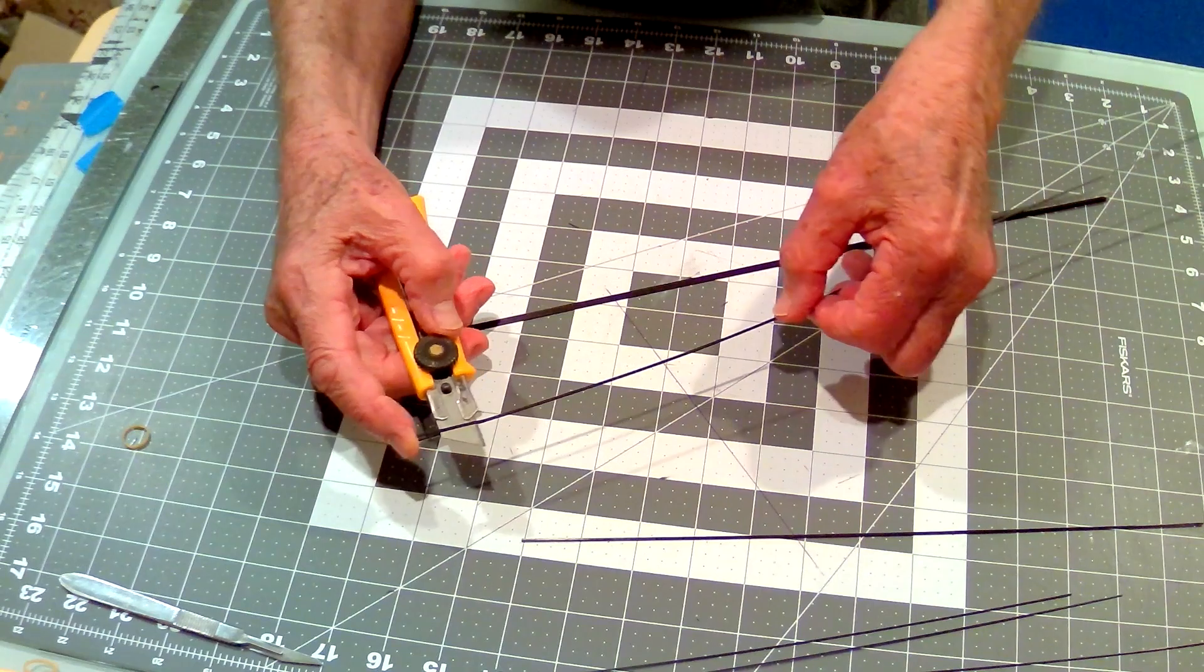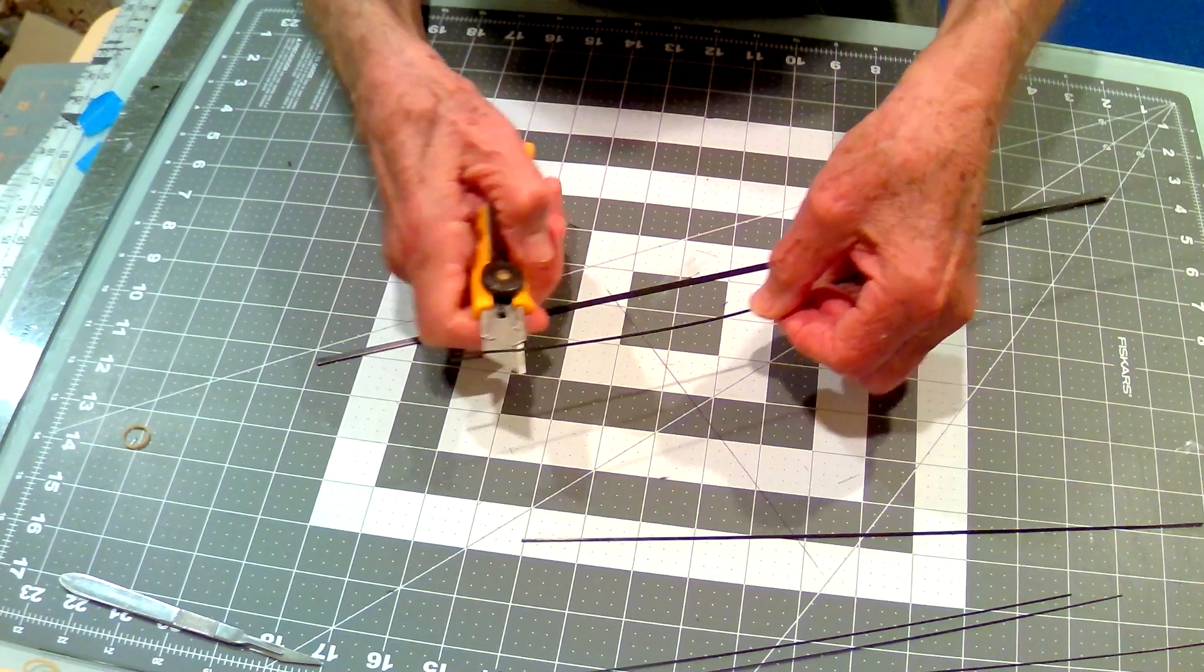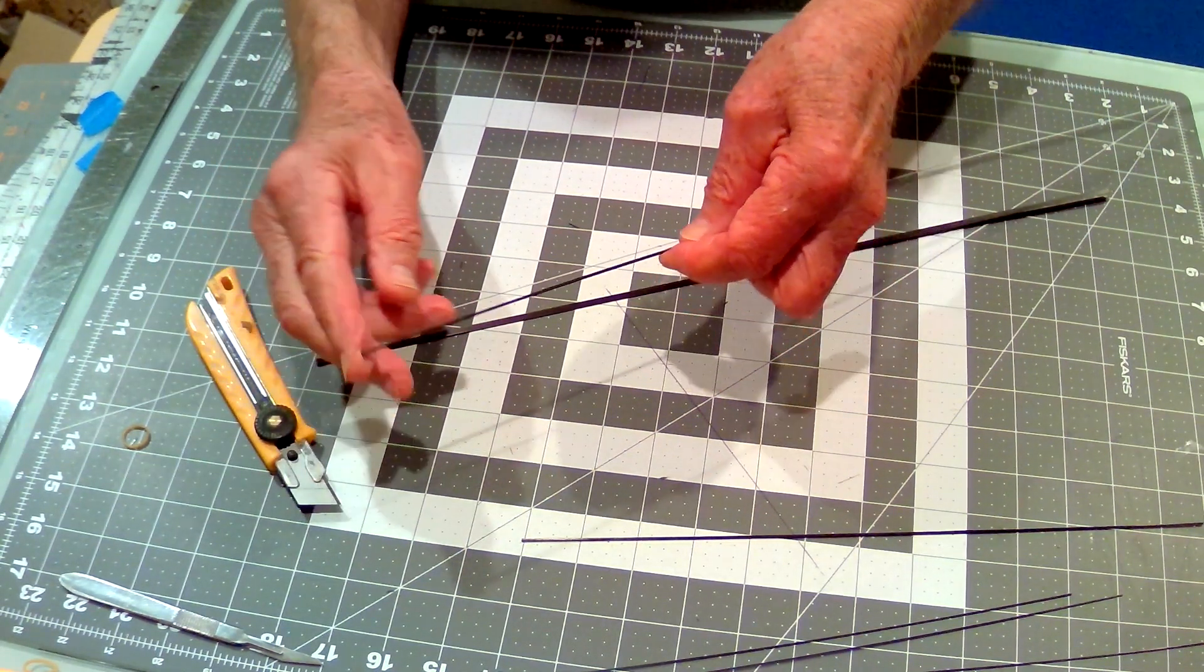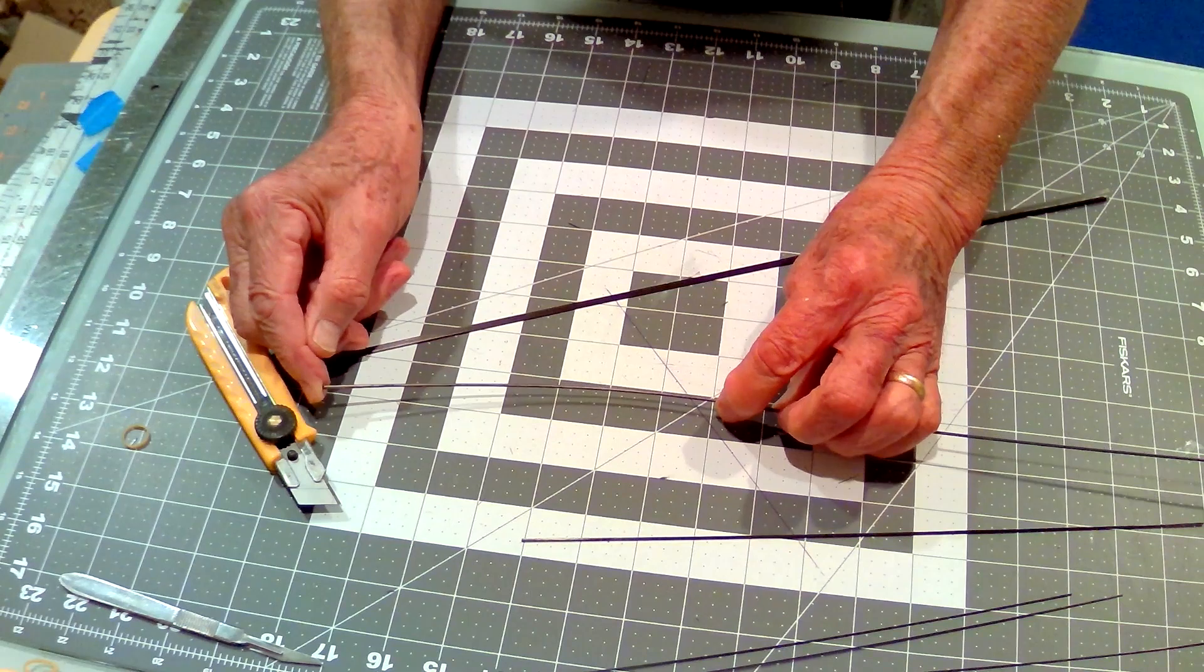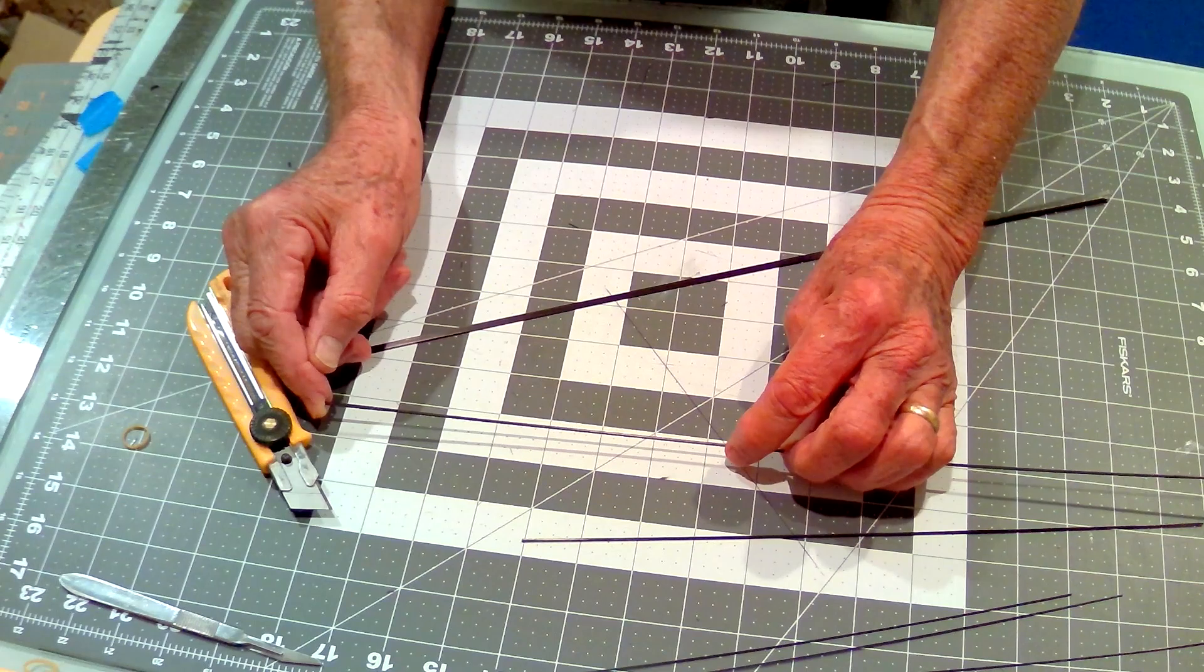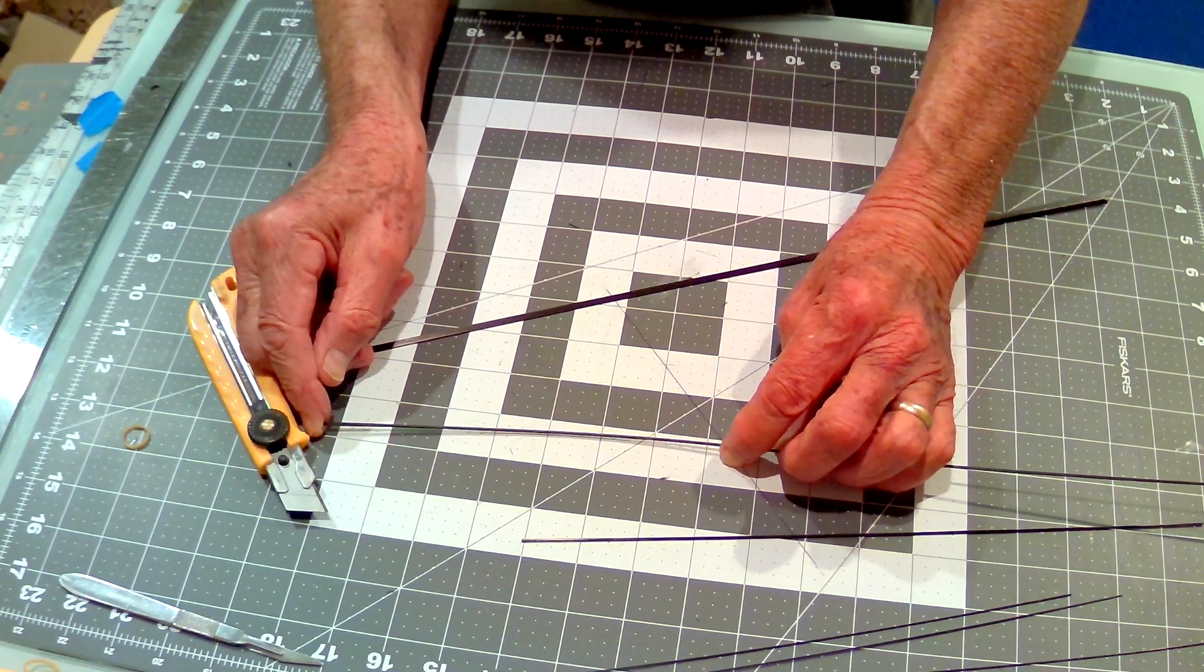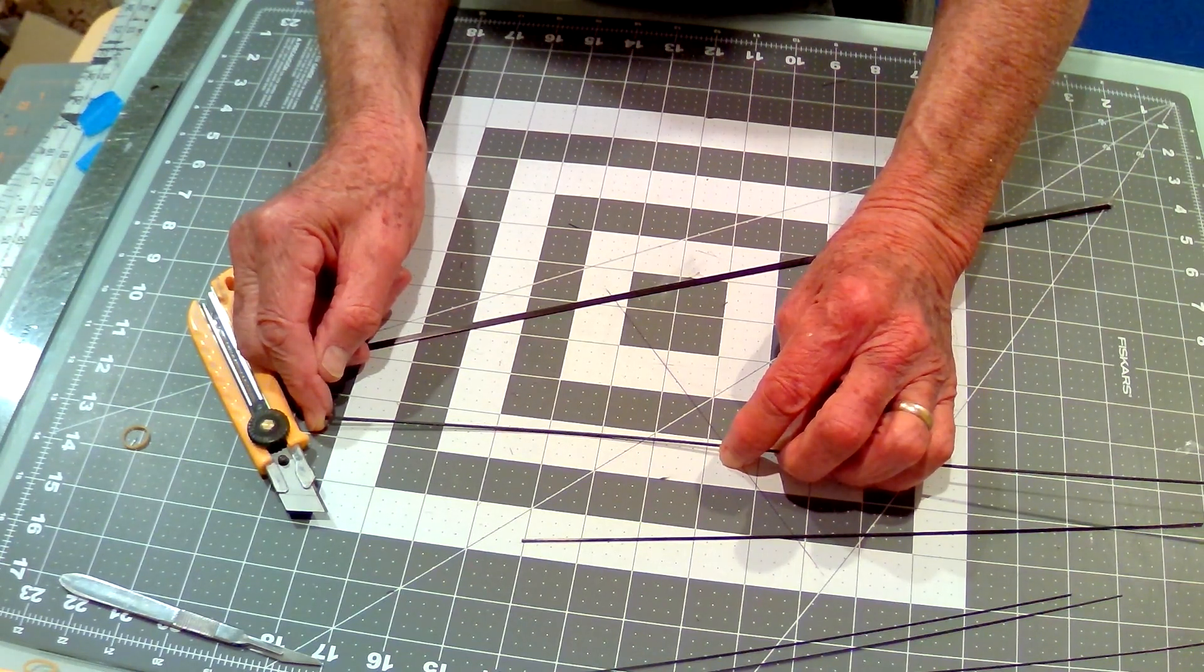I can split this rod along the length where I want the bend in my spine. Then I super glue it back together and clamp it in a form that shapes it how I want. When the glue is dry, I release it. Although you'd think it would stay exactly where it was glued, it doesn't—it does slightly reduce the amount of curve you clamped it to.